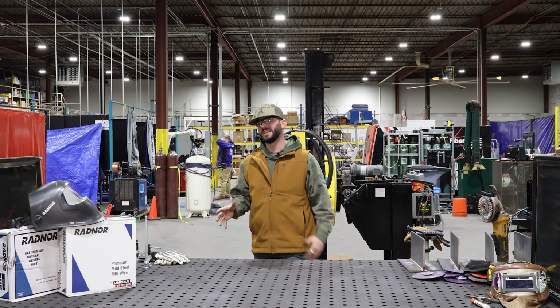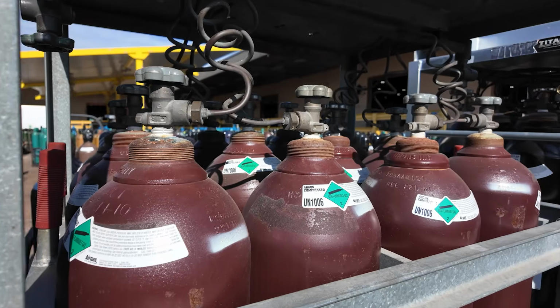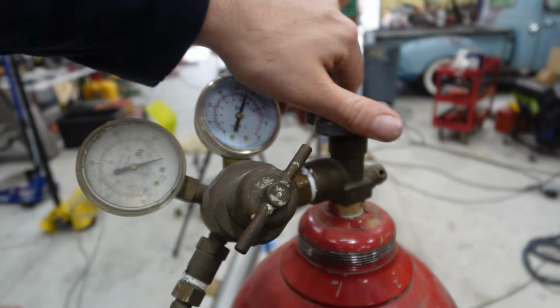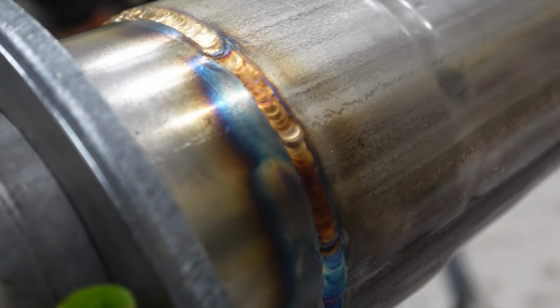One of the most common shielding gases that I personally use often is argon. 100% argon I've used for a whole bunch of stuff, and you can weld a whole bunch with it. It's a great shielding gas for arc stability, keeps the weld cool, free of defects, the whole nine yards. And fun fact about argon, it's actually heavier or denser than the air that we breathe. So it settles in low points of whatever container it's in.